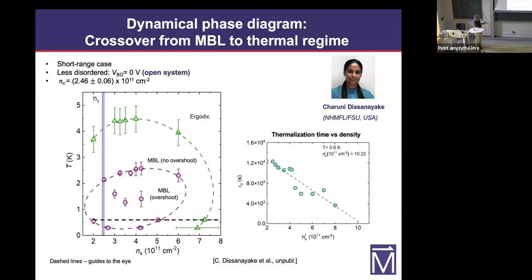We also looked at, for example, thermalization time as a function of density along these lines at a fixed temperature. And again, you see as you increase the density, this thermalization time decreases by more than an order of magnitude, eventually vanishes. So this is not surprising, as we are moving towards the metallic regime. So the system does reach thermal equilibrium. Nothing strange happens at higher densities or temperatures.